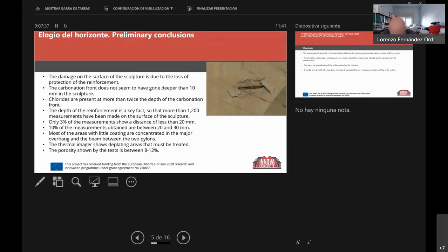Gijón is a very industrial site, and the industrial area is close to the site of the sculpture, and also we have the sea. The salt coming from the sea. Most of the reinforcements were deep enough, but we took a lot of measurements of where the bars were, which depth we had, and only about 3% of them were